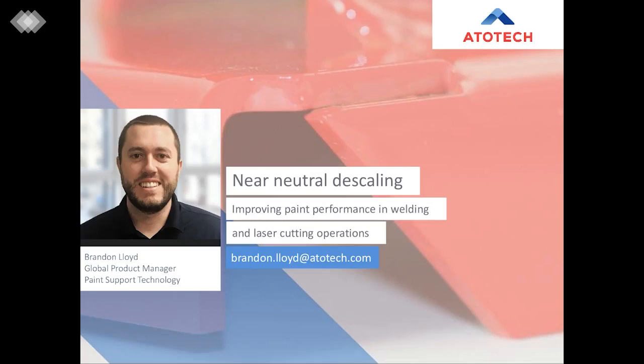Sure. So in the evaluations that we've done and some of the implementations of our Uniprep AC products at customers, we have seen that the burn area can present as much of a problem to applicators as the scale on the weld itself. So these heat affected zones appear on the front, and depending on the thickness of the substrate that's being used, can appear on the back as well. This is especially troublesome for welds on tubular pieces or those with line of sight issues, making it impossible to mechanically remove prior to paint application. So the implementation of Uniprep AC for these types of applications really offers a big benefit where line of sight is an issue for the burn areas.